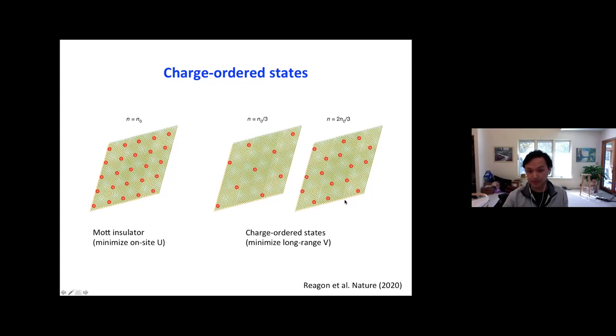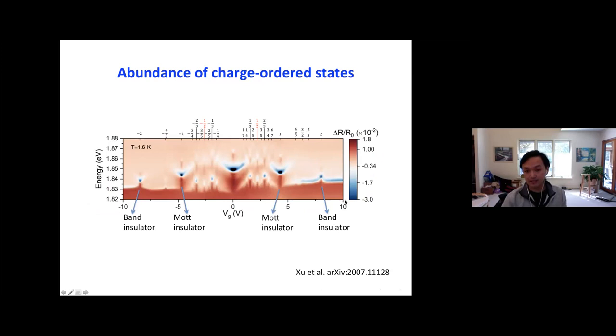Just to highlight, with a new detection technique, which I probably don't have time to go through, and improved quality samples, we can now see not just two of these additional fractional states, but close to 20 of them in the system. This shows an example of the data we get on this high quality sample. This is the gate voltage, which tunes the filling factor from negative two all the way to two. Negative means hole doping, positive means electron doping of the same material system.